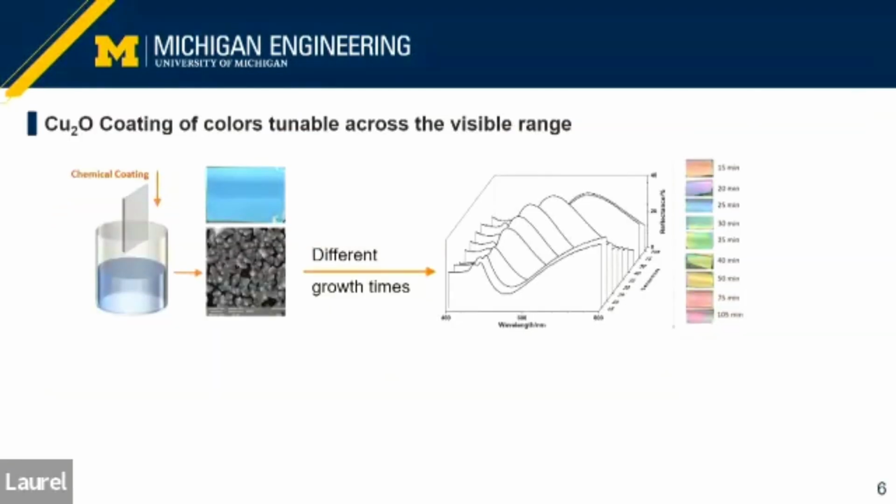My advisor assigned me the work to find out what caused this phenomenon, how we are able to reproduce it, and even to make a uniform color out of it. After a lot of trials, we finally found the right recipe. For this method, by just immersing the substrate into the growth solution, after a certain time you can produce this large area of cuprous oxide of octahedral morphology. Octahedral morphology just looks like this.